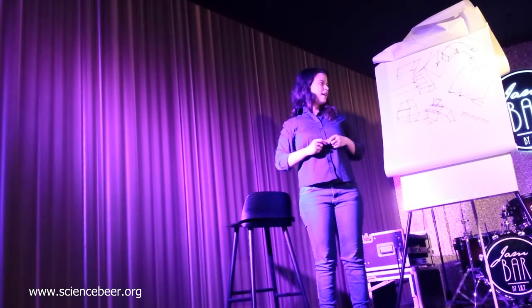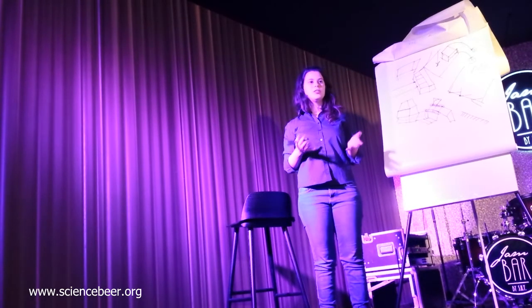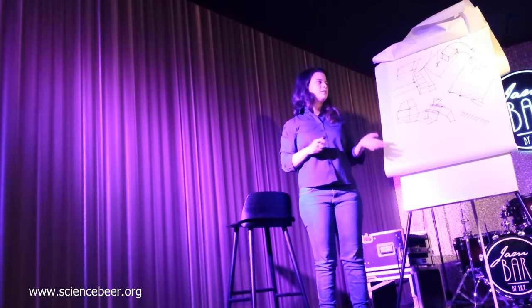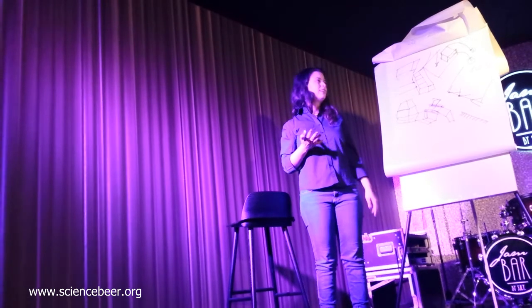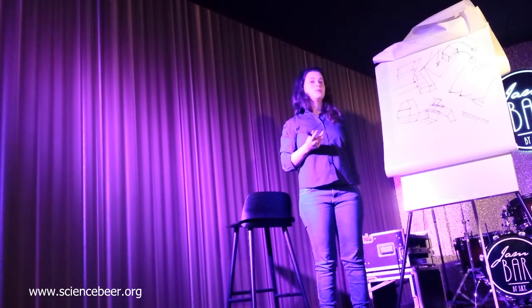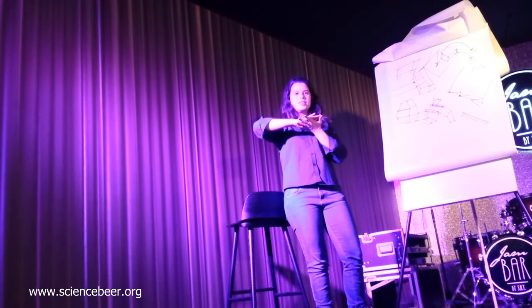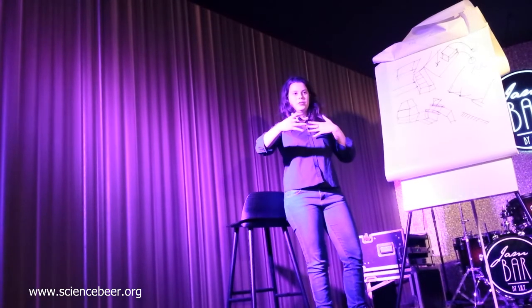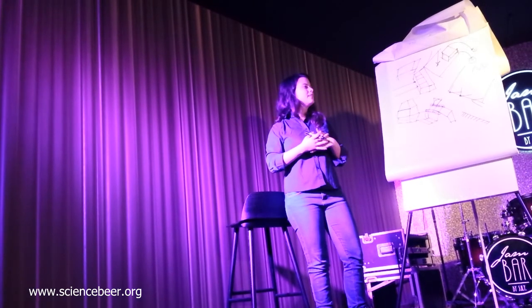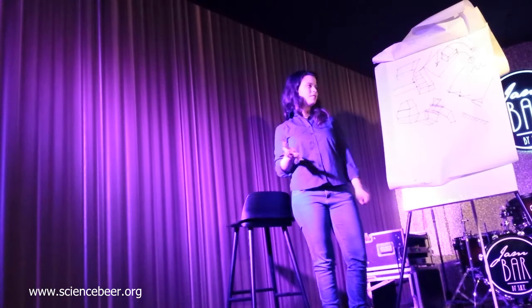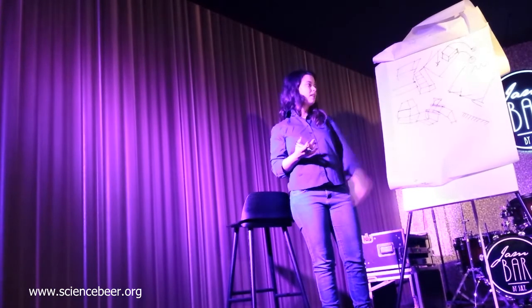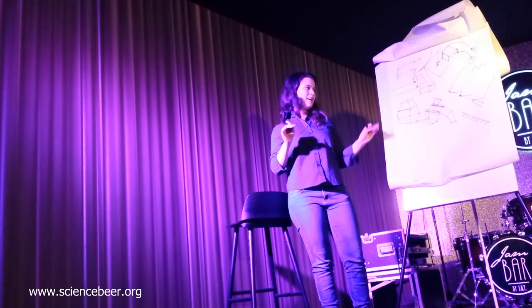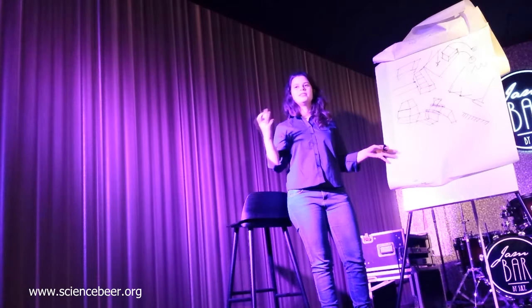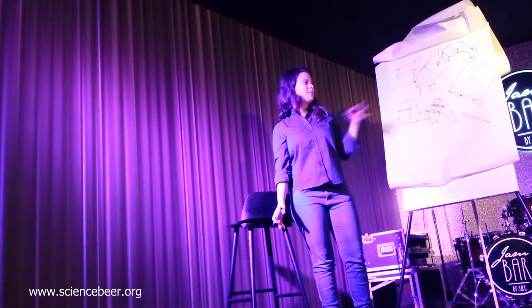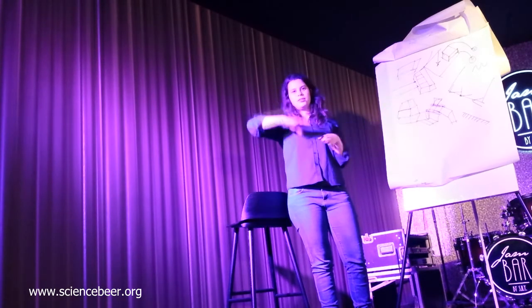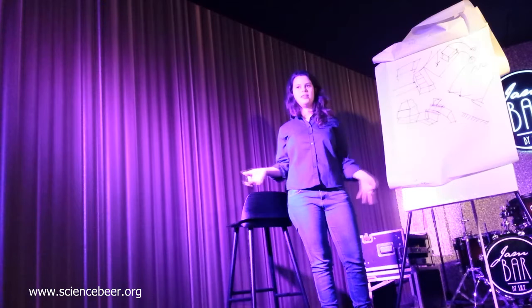And some things that I have seen, these are some initial results, were for different materials, different concentrations. They work a bit different from what we expected. Sometimes it compresses the material, sometimes if it's an open film it can close the film, but this is a lot of handiwork. The shearing process, the crystallization process, is a little bit tricky. Various tiny factors make the output look quite different, so it's difficult to evaluate what is done by our vibration mechanism and what is not done by it.